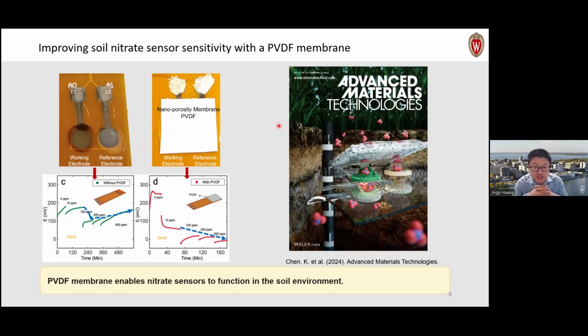membrane. This nano-sized membrane is going to act like a wick. It's going to suck the water close to the reference and working electrodes, so it creates a relatively humid environment around the nitrate. When we did this lab testing with the soils, we noticed that if we don't have this membrane, which can provide a humid environment, the equilibrium nitrate level we detected for different nitrate concentrations has no linear response with the voltage of the electrodes.